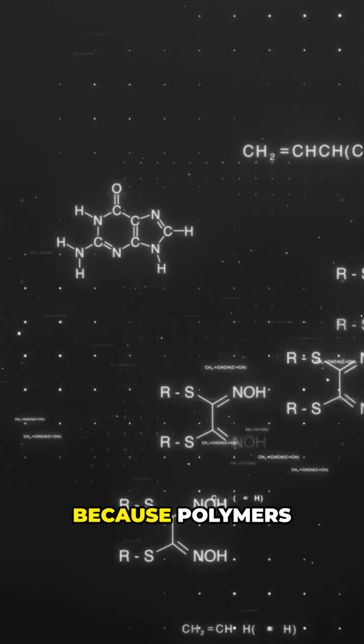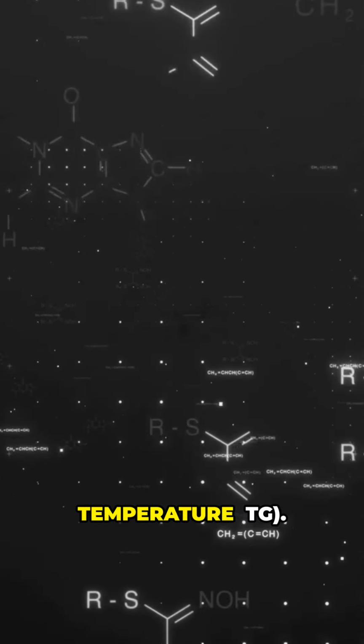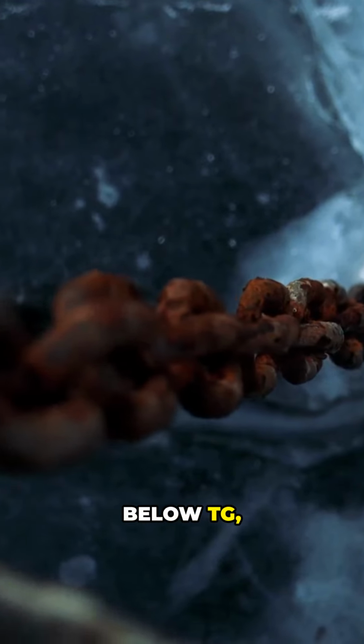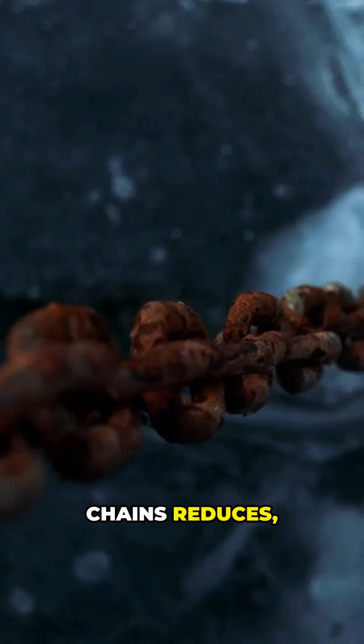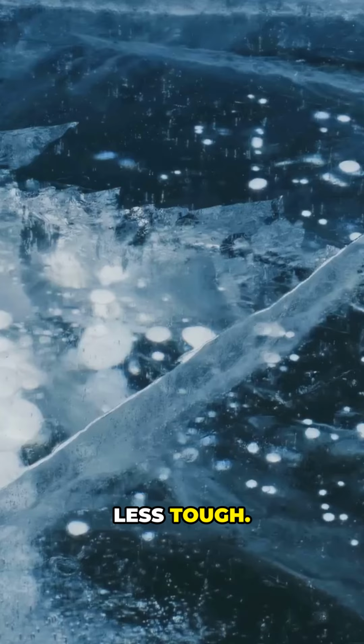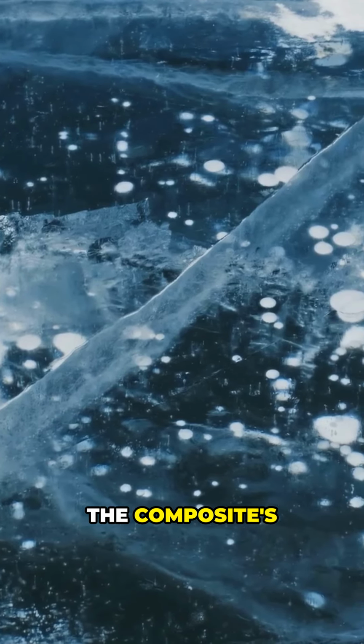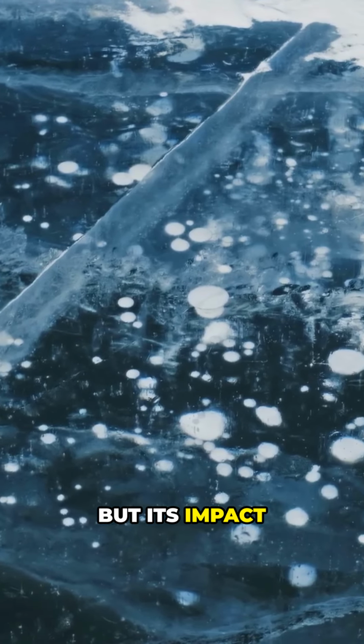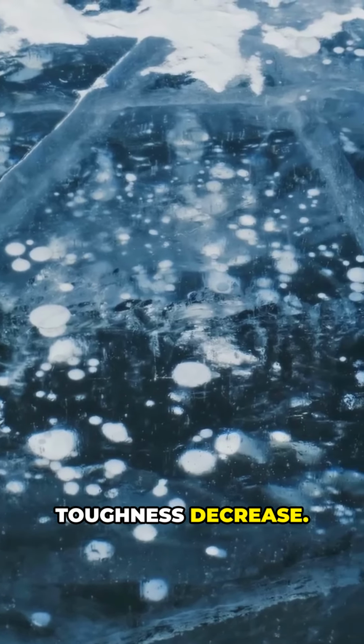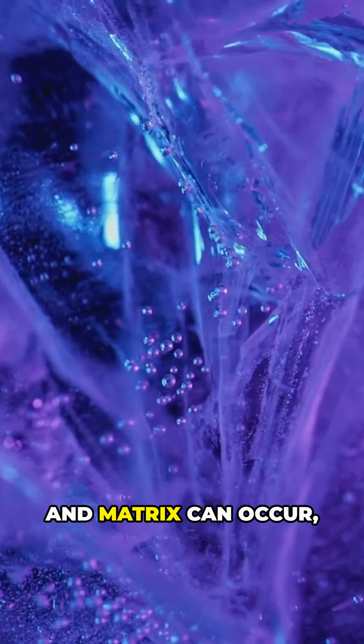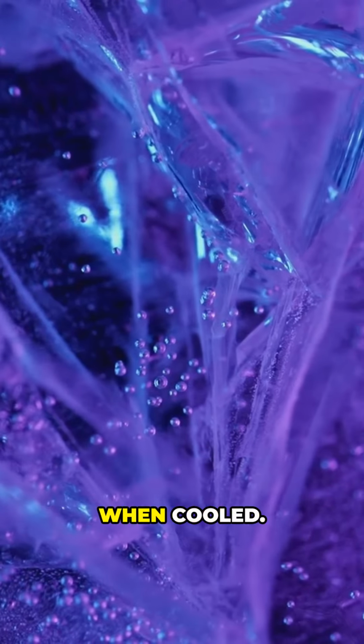At -50 degrees Celsius it becomes stiff and brittle because polymers approach their glass transition temperature, Tg. Below Tg, mobility of polymer chains reduces, making the material less tough. So, what happens overall? The composite's stiffness increases, but its impact resistance and toughness decrease. Micro-cracking between the fiber and matrix can occur because they contract differently when cooled.